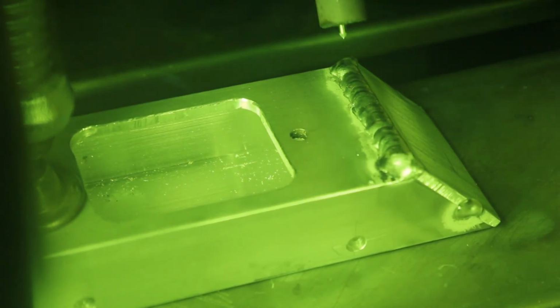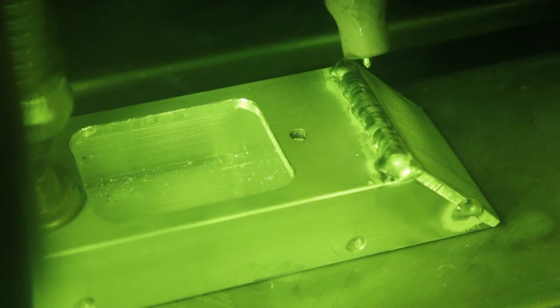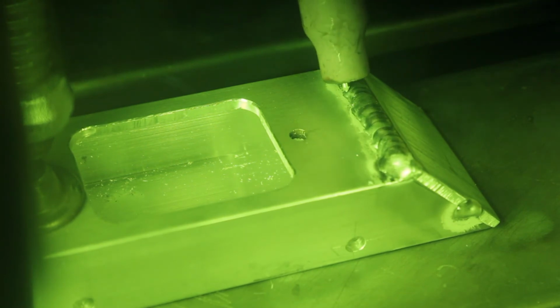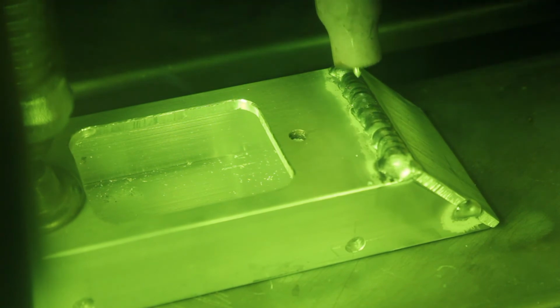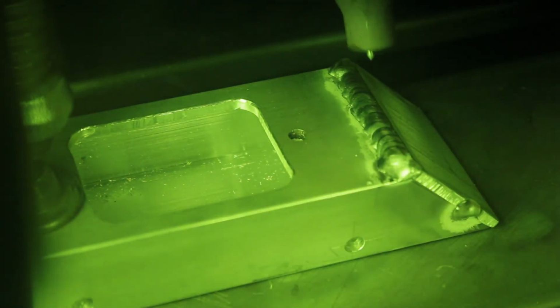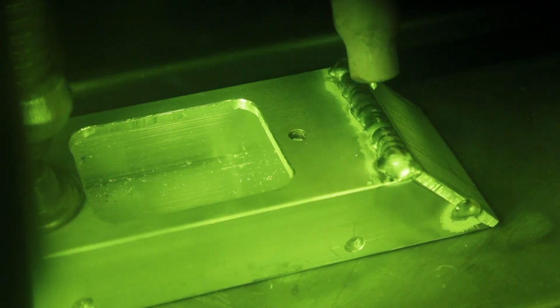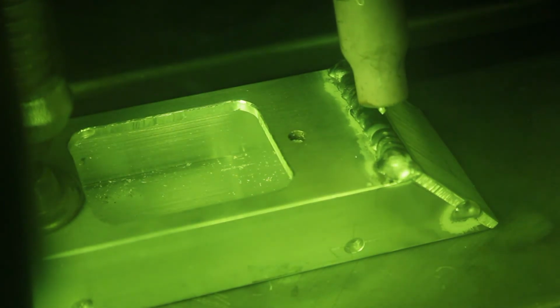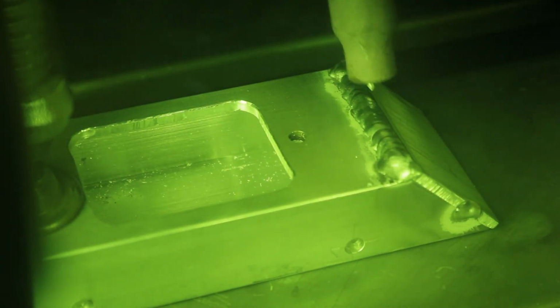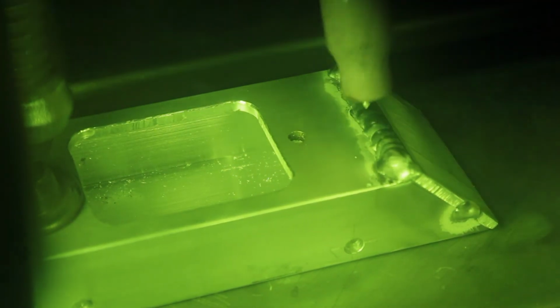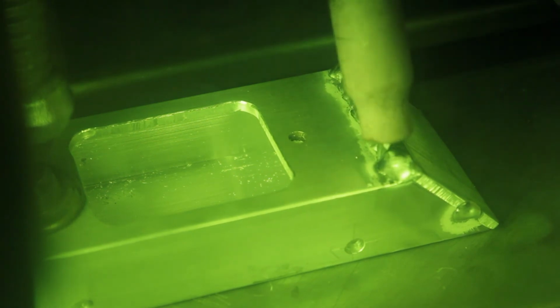And that's what a proper weld should look like. If it's too bulging, so if the weld sticks out too much, then it's not enough heat. And the metal, the filler rod is just melted on top of the metal. If it's concave the other way, then it's too hot and the metal has seeped into the base material. So you kind of want a slight dome here and these little ridges along like this.